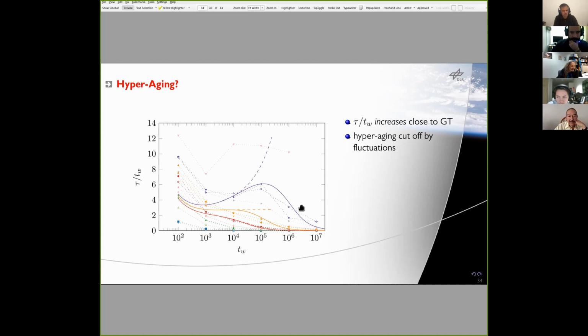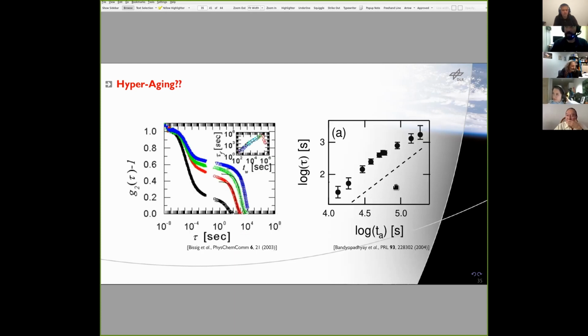I have been looking a little bit in the literature for observations of such hyperaging regimes. And I didn't find many good data, not in structural glasses. I found a few in gels, and the solid data is basically, I'm showing you this slide to say you have to believe the authors, because it's all in this inset here where they show the relaxation time as a function of the waiting time. And now you have to zoom into your zoom window to see whether this is linear or slightly superlinear. And the claim in the paper is it is. Also here, you have to go to the original references and blow up the PDF by 400%, and then you can perhaps see it. So I think there would be further room for experimental or computer simulation support of this.